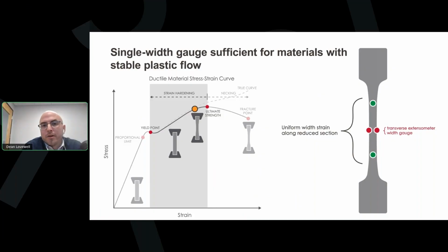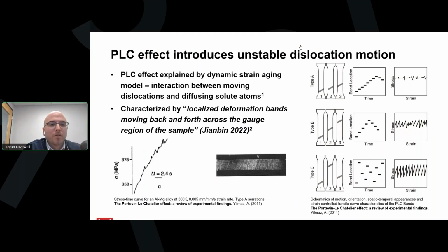And then just another reminder here, you can tell that this is the reason why R values are never calculated past tensile strength determination, since again, after the specimen has received maximum force, it'll neck locally, and those red dots will no longer be representative of the full specimen. So the PLC effect complicates this method by what's observed as jerky flow of the specimen.